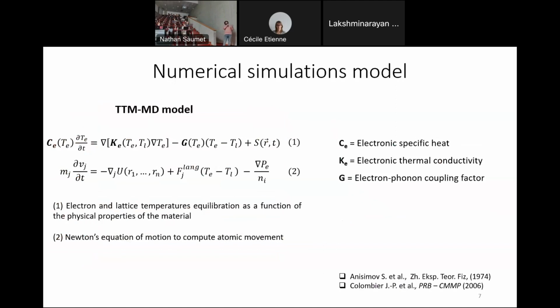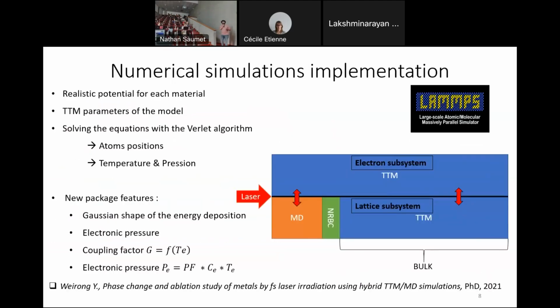For this, we chose to use the TTM-MD model, which is a coupling model between molecular dynamics, represented here by this second equation, and TTM, a two-temperature model, which makes the link between the electronic temperature and the lattice temperature, depending on the material and the electronic temperature, through the electron-phonon coupling factor. To implement such a model, we're using LAMMPS, which allows parallel calculations, allows setting all the different parameters of the two-temperature model, and simulating the deposition of the laser energy.